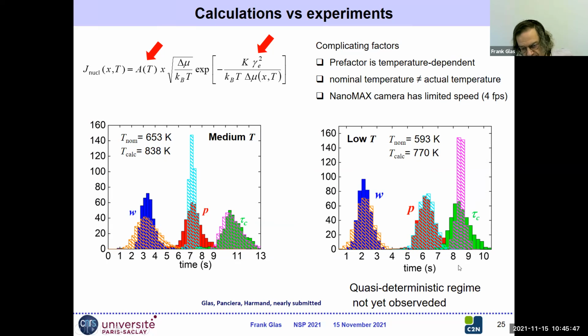So the conclusion, which is slightly sad at the moment, but it gives us a margin of progress, is that the quasi-deterministic regime that we predicted from the model, the fact that tau c should be very narrowly distributed, has not yet been observed. And part of this is related to the limited time resolution of the camera. So if we go to a high-speed camera that we have now, then things might get better, but it's still not clear if there are some fluctuations in the system that we have not considered that would intrinsically broaden this distribution or not.